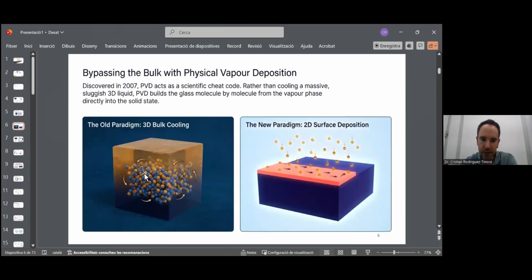Now, on the left you see this scheme where we have the bulk of the material, where the molecules or the atoms, as we reduce the temperature, try to relax, try to stay in equilibrium. But since every molecule here is surrounded by many other molecules, this relaxation process is difficult for them. Every time it's more difficult. But in 2007, the group of Mark Ediger found a new strategy to form glasses which were more stable, which means a way to prepare glasses, keeping them in equilibrium down to lower temperatures. And this was based on vapor deposition.